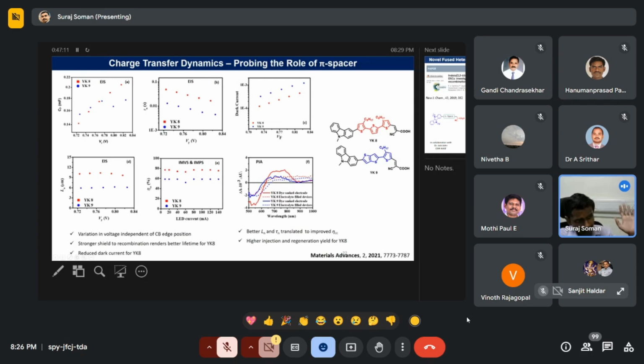Then you measure the lifetime. So from the lifetime, you can see that the YK8 sensitizer has a better lifetime compared to YK9. And similar is reflected in the dark current. The dark current for the YK8 is less. And the diffusion length is better for the YK8, and that improved the charge collection efficiency.